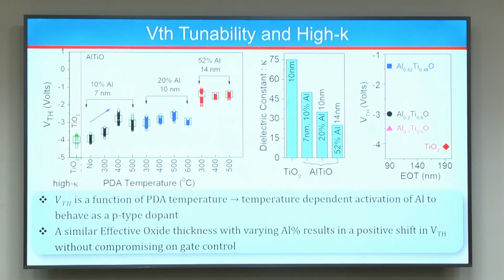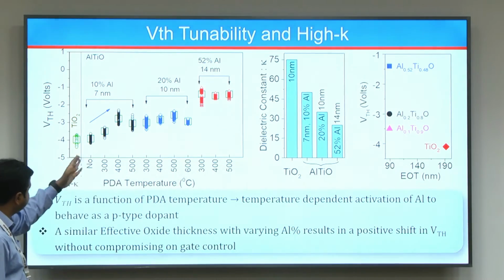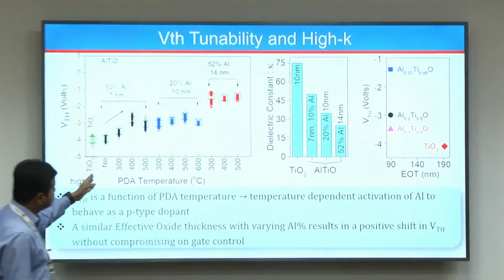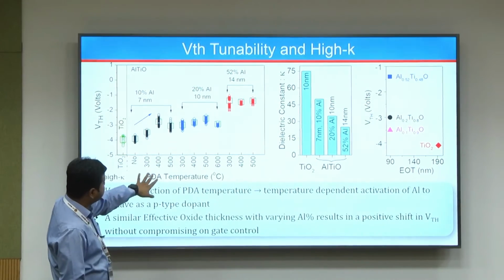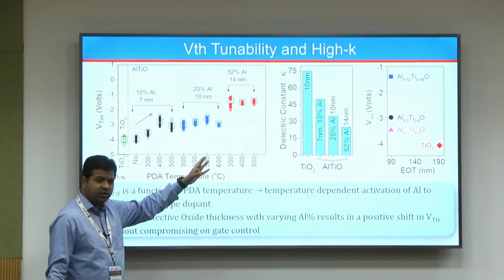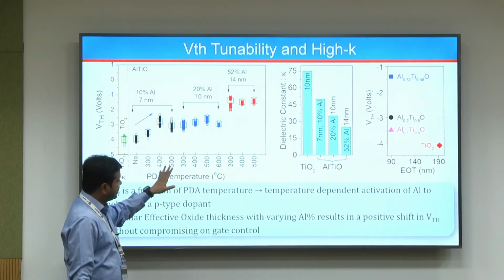So I have only 5 minutes left, so I'll skip a few slides. We did a lot of optimizations in terms of activation of these charges. What is the right temperature at which they will activate. We compared with titanium dioxide. We also compared, the data is not in this one, we also compared with nickel oxide and copper oxide gate dielectrics.